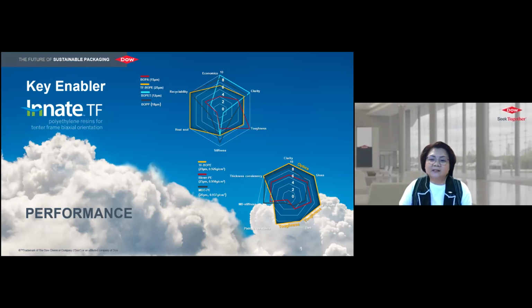Conventional PE resins are difficult to stretch under the conditions due to narrow stretching window. Dow has developed and launched a new resin called Innate TF80, which has superior processability on industrial scale tenter frame line. After the high level orientation, PE films get outstanding physical properties and narrow gauge variation, which is ideal for printing substrate or toughness enhancer layer for all PE structure.